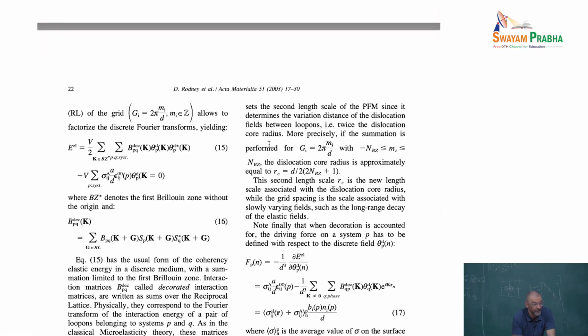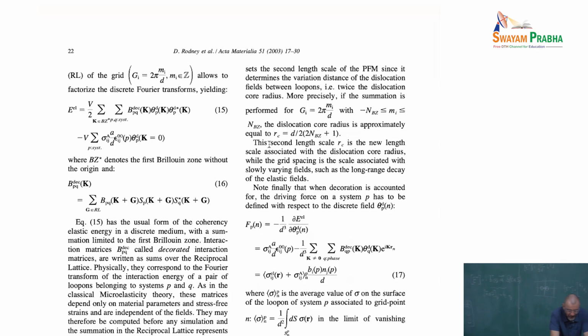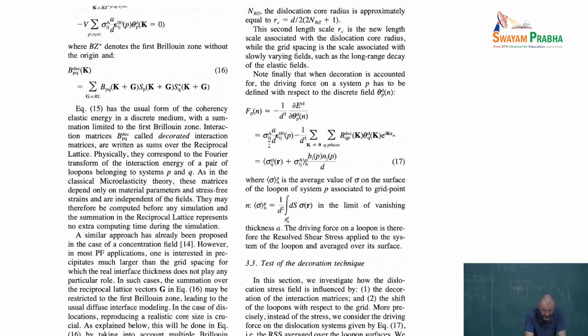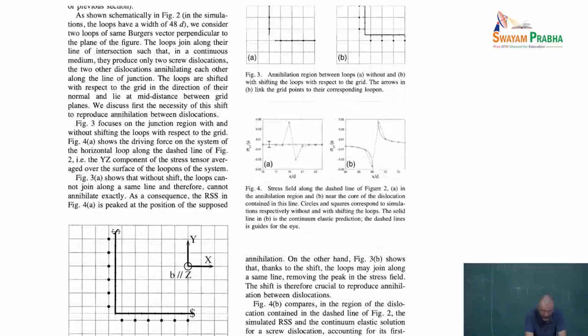There's some math involved, but what we are writing here is exactly what I said here, nothing more, nothing less. What is good is that for the dislocation, the assumption that the elastic constants are homogeneous makes sense because it's the same material inside and outside, right? So in the case of dislocations, that's not the issue. The issue is how you stabilize the core width of the dislocation, and most of the paper is some mathematical tools to try and control the width of the dislocation core.